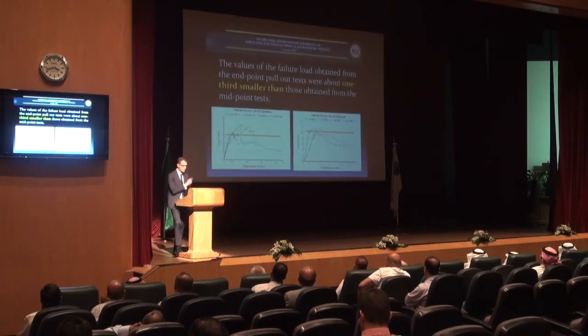Of course, we have obtained load-displacement curves and also the failure mode for all the beams that we have investigated, with some conclusions, for example, that the value of the failure load obtained from the endpoint pull-out test was about 1/3 smaller than those obtained from the midpoint test.